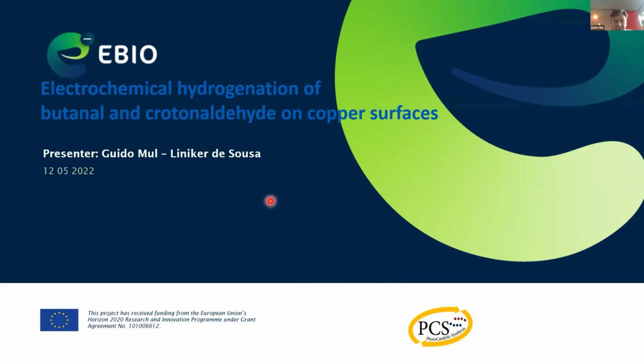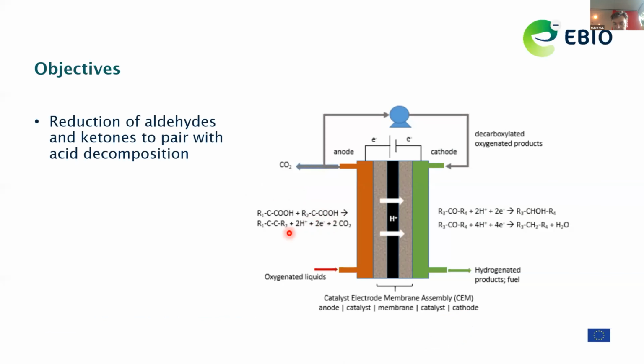Yeah, so I will be discussing a little bit more on the hydrogenation of aldehydes. Bastian showed a very nice slide with the distribution of components in pyrolysis oil. And in fact, besides the acids, also aldehydes are components that destabilize the pyrolysis oil and need to be converted, preferably to alcohols. And electrochemical hydrogenation could then be a very nice way to pair up with a Kolbe oxidation reaction in a sort of combined electrochemical process, which you see over here. So if we have the oxygenated liquids, the pyrolysis oils, coming in and first do the Kolbe to remove the CO2 and the ethane in case of acetic acid.